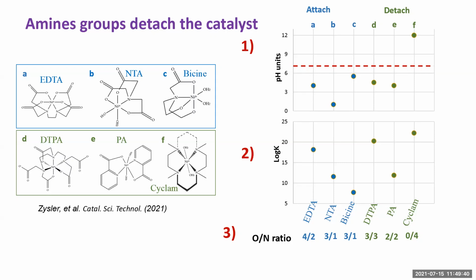My question is that okay, you have this conclusion for the chelating agent specifically, but how do you know it's also right for the doping? Well, we don't know exactly if it's right for the doping, but the idea is to consider that if you dope with nitrogen or if you have different nitrogen groups inside your support, maybe this will detach your particles. So okay, it's not something you actually tested. No, because for this we need to dope the carbon and to test exactly the difference, the same particle, doped and not doped. Okay.